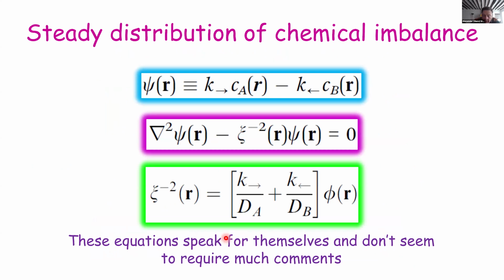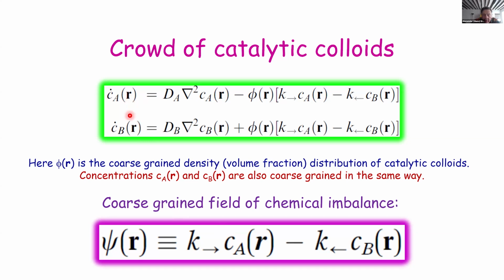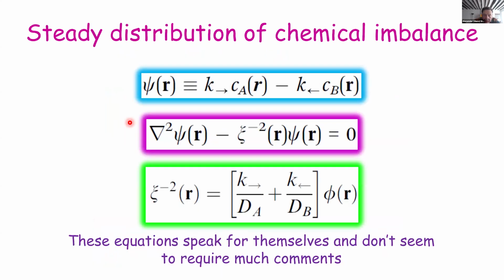So in steady state, if you forget about time derivatives here, you study the steady state distribution of fuel and exhaust molecules, and you discover that, of course, this steady state distribution describes this chemical imbalance function in this familiar form, where the screening radius is given by this formula. So the screening radius is, of course, inversely proportional to the square root of the concentration of these colloids, which is absolutely not surprising because the Debye radius, of course, depends on concentration in the same way. And there is this factor which is controlled by rates of reactions and diffusion coefficient.